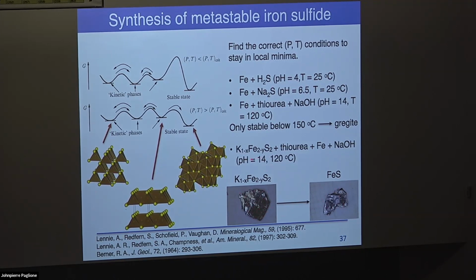And this can be done, again, hydrothermally with pretty much the same conditions. So this is what we call a bottom-up synthesis. We're making iron sulfide from the bottom up from the constituents. And this is what we might call a top-down synthesis, where we're taking the building block iron sulfide that has the right layers from this compound and basically converting it into the target compound. I'm not sure exactly if this is the exact crystal turned into this one. I'm pretty sure it is, I don't want to say exactly, but this is the type of single crystal conversion we can do with hydrothermal synthesis, for example.